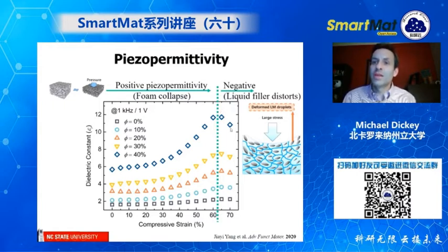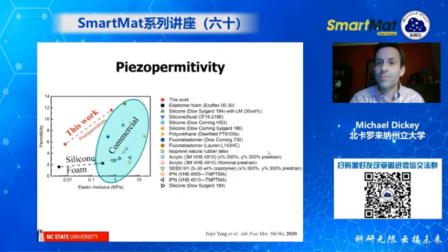And the reason that we think it's going down is because the liquid metal fillers are actually changing shape. And that change in shape actually changes the dielectric constant, which is really fascinating. As far as I know, this is the only example of a material that does this that's reported. That is liquid metal fillers.